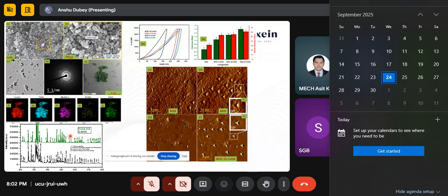And again, we checked all the mechanical properties. This portion shows the nanoindentation studies, and we took the indentation in a particular grain and found that the mechanical properties were enhanced compared to the normal hydroxyapatite which we were using in the previous slides. So we could say that we can modify the HA with magnesium and zinc ions, co-precipitate it, and get good results in terms of mechanical properties.